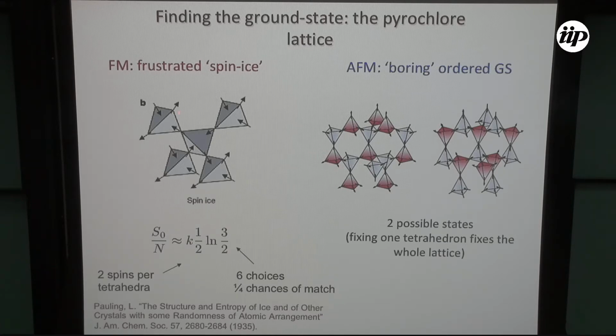Okay, so this was the interesting spin-ice state. And then the boring state, as I said, only has two possible ways. Once I choose one of the tetrahedra to have all of them pointing in, those will be the blue ones here. Then the next tetrahedron has to have all of them pointing out. Those are the red. And once I decide one tetrahedron, all the rest fall in the same direction. So the residual entropy for that state is 0.